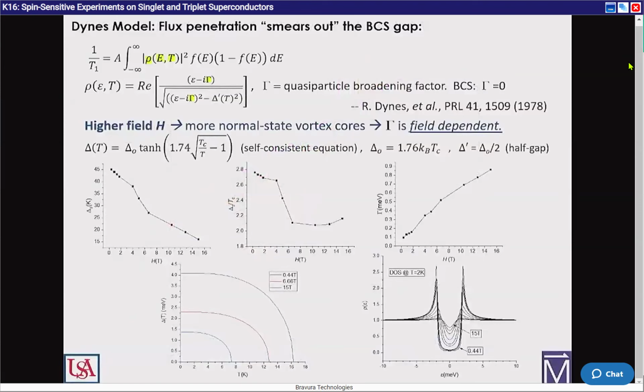Dynes came up with the idea of starting with the BCS density of states. You have this additional parameter called gamma, and that is a measure of the broadening of the quasi-particle lifetimes as you introduce some kind of pair breaking mechanism. So you've got Cooper pairs pairing and unpairing at the edge of the gap. And when we use this form with gamma as a free parameter, well, delta is kind of free, but it's still constrained by the TC of our data.